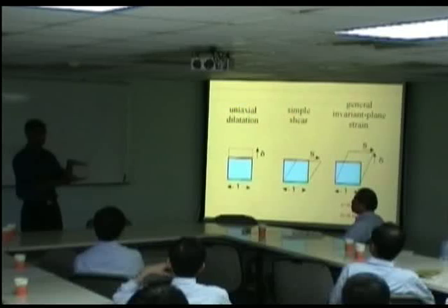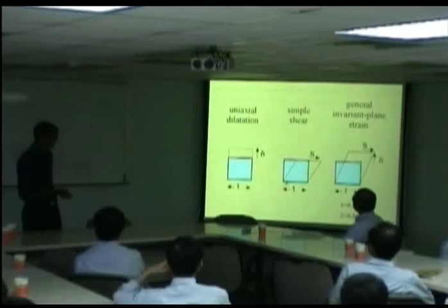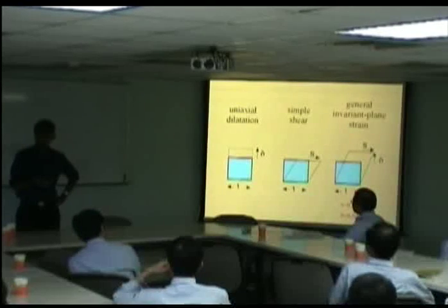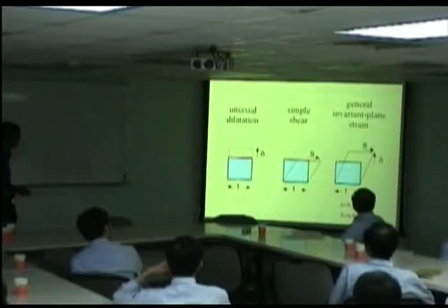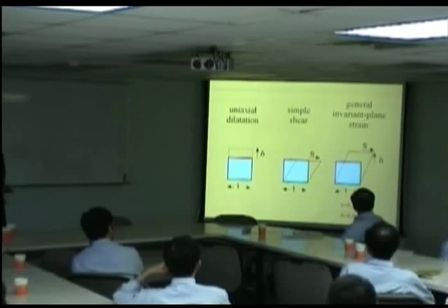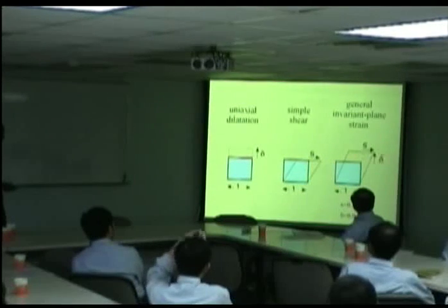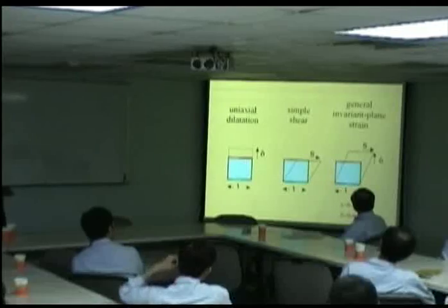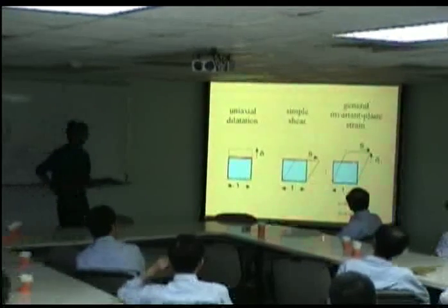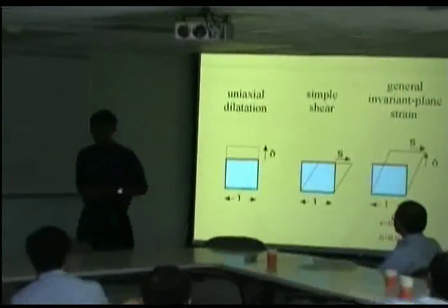Now, when we look at ordinary slip deformation, it's a shear. But again, it leaves this plane completely unchanged. That's an invariant plane. If I combine these two deformations, then that is the sort of shape change accompanying martensitic transformation. There's a shear deformation and there's a volume change normal to the habit plane. So when we do measurements, this is precisely the sort of shape change due to martensitic transformation.